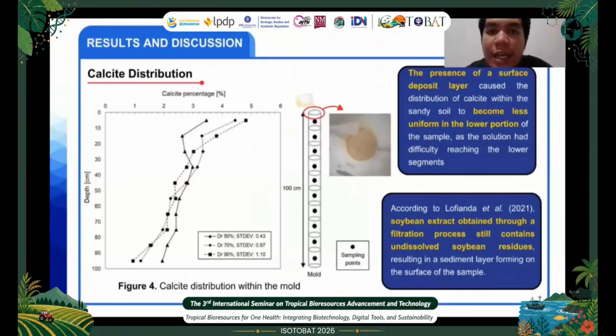In contrast, in the sample with a relative density of 90%, the narrower pore space limited the penetration of the solution into deeper layers, causing calcite to concentrate in the upper portion of the sample and decrease in the lower segment. This phenomenon was further exacerbated by a layer of residual soybean extract deposited on the surface of the sand sample, which hindered the solution from reaching the lower layers of the sand.